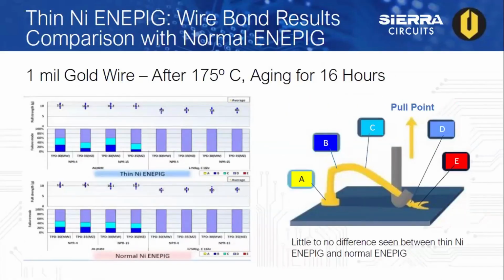Here we have wire bond test results comparing thin nickel and standard ENEPIG. The conditions of testing were using 1 mil gold wire on as-plated samples, and then samples heated at 175 degrees Celsius for 16 hours.